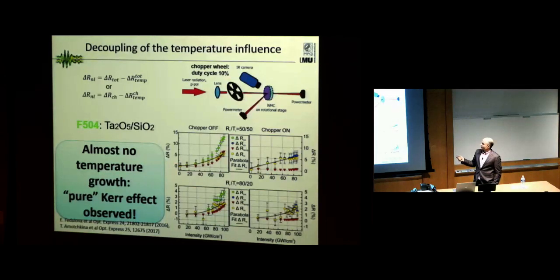And you see that when we introduce the chopper, we can split the result, which shows that there is a thermal shift, because the laser has a high power and we still have changes in reflectance due to the change of temperature of the sample. And here you can see that for quite some intensity, we can see 5% changes due to the Kerr effect, which is really a fantastic value. We observe this also for this curve, shown for the chopper off, and this curve, shown for the chopper on. In this case, the thermal effect change is also about 5%, but when the chopper is on, the thermal effect is almost nothing, and the nonlinear effect still remains there. It means the Kerr effect is still working in the structure. It's the same behavior we observe for another ratio when we change the angle of incidence.